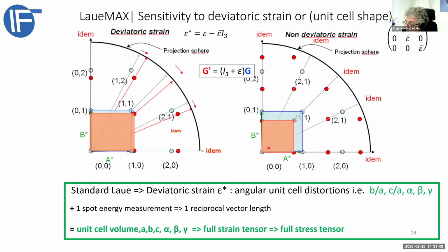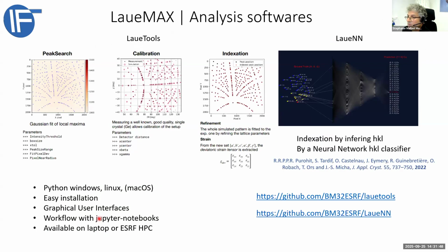Okay, and I don't want to go into detail, but actually with this technique, the standard way, when we measure the Laue pattern, you have only 5 of the 6 lattice parameters because we don't know precisely the energy. For the moment, we don't determine the energy experimentally. So the length, the distance in reciprocal space between the node and the origin. But if you add the measurement of one Laue spot energy, then you have the 6 lattice parameters. And then for people working in mechanics, you can have access to the stress, which is very, very valuable.